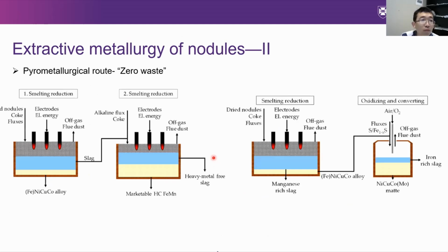So another extractive metallurgical route is the pyrometallurgical route, which is zero waste, to fully use the nodules. First, the dried nodules, coke, and flux are charged in the electric furnace to produce manganese-rich slag and iron, nickel, copper, cobalt alloy. And this manganese-rich slag is further directly fed into another electric arc furnace to produce marketable high carbon ferromanganese alloys, and then leave heavy metal free slags.